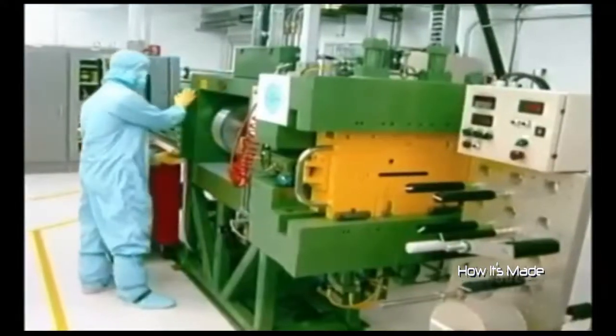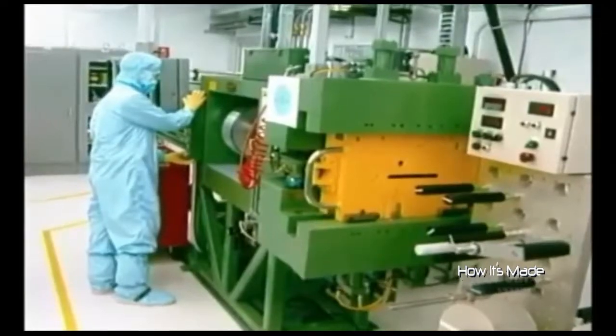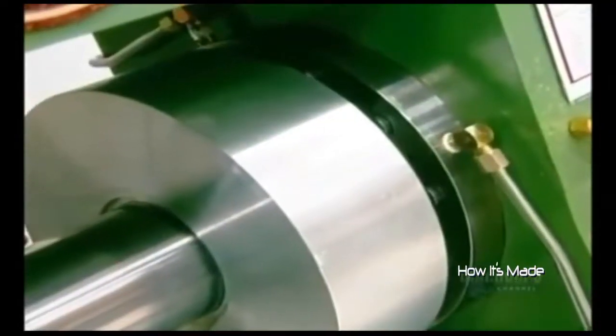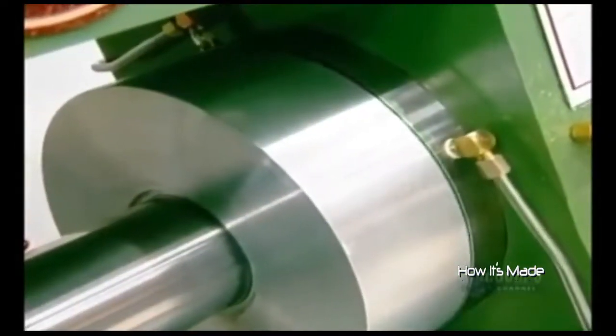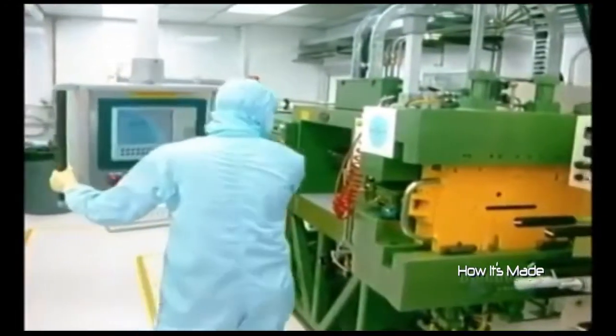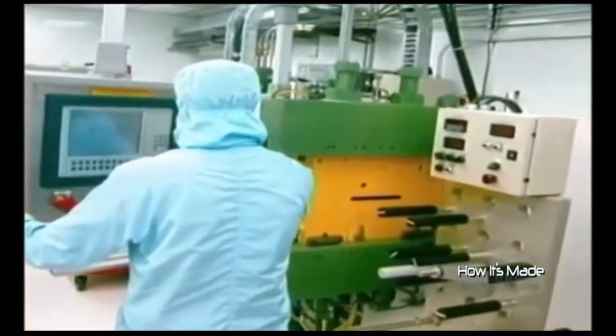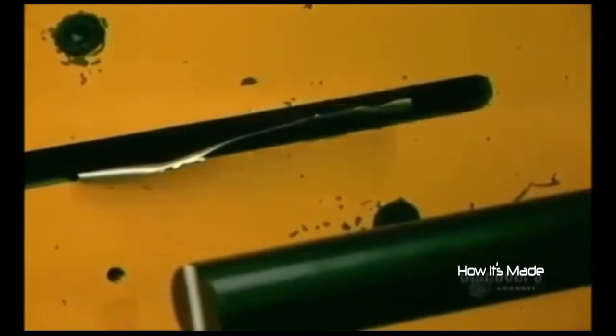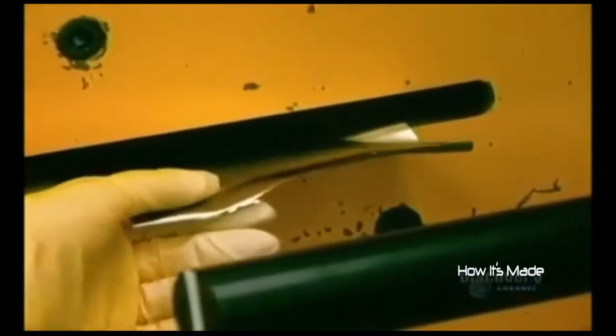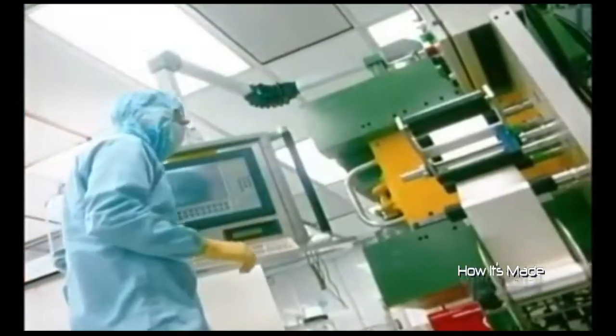It's transformed into a thin sheet by this extrusion press that applies 400 tons of pressure. From it will exit a sheet that's only about 250 microns thick. The whole extrusion sequence is closely computer controlled. Extrusion is now completed. The metallic lithium sheet is the required 250 microns in thickness, or 1/4 of a millimeter. The sheet has to be further thinned.